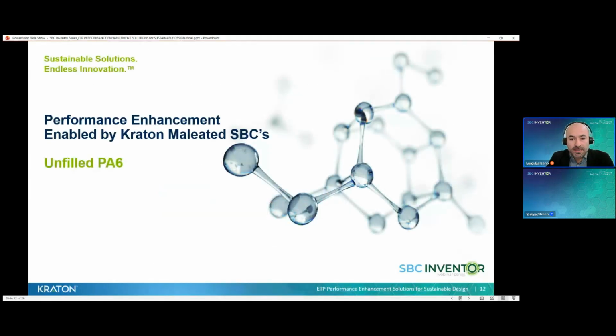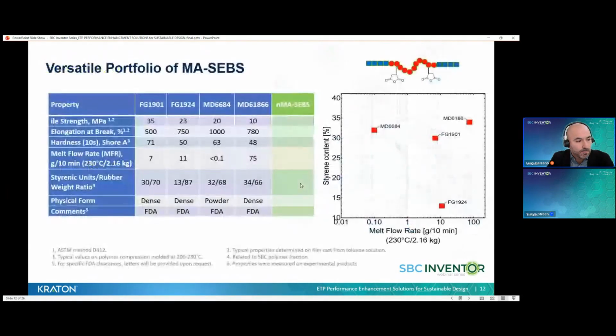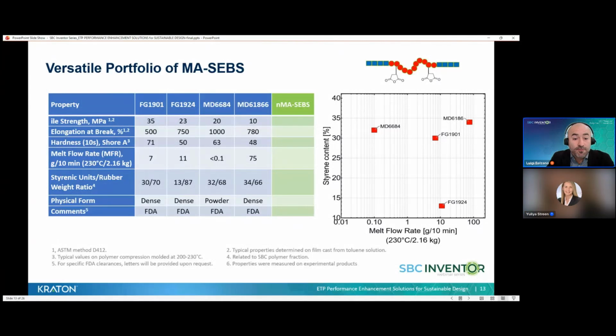In the coming few slides, I will show some examples that demonstrate how Kraton maleated block copolymers enhance the properties of unfilled polyamide 6. Kraton has a versatile portfolio of SEBS functionalized with maleic anhydride. There are 4 main products that differ mainly by styrene content and melt flow rate, as shown in the table on the left and in the plot as well. All these grades are suited for polyamide modification and adapt to varying application demands. The choice of the grade depends on the details of the target performance.